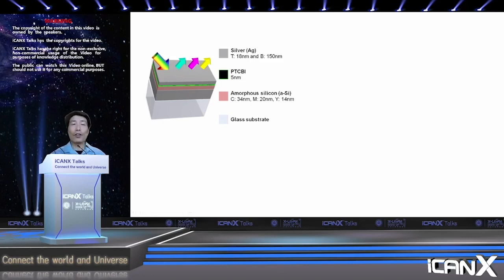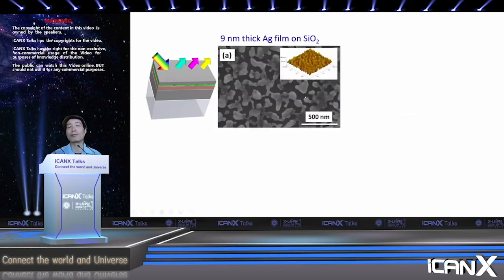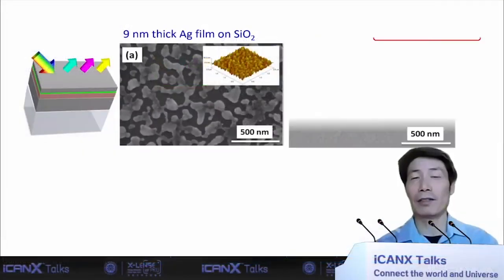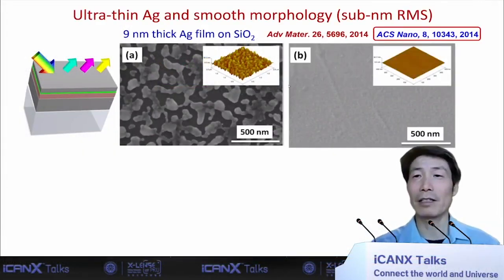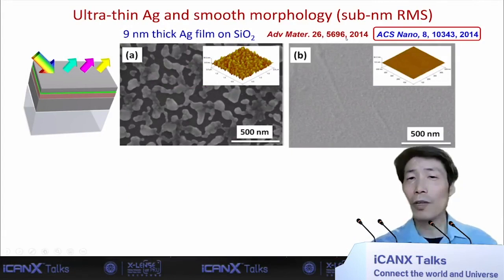Getting silver to be very smooth, for those who have actually done deposition, is not easy. For instance, if you deposit 9 nanometers of silver onto glass, it basically becomes grains. It may not even be connected, so it may not be conducting. It has huge optical loss as well. But we came up with a strategy several years back. So you can see that now we can produce a few nanometers of silver, very smooth and thin.